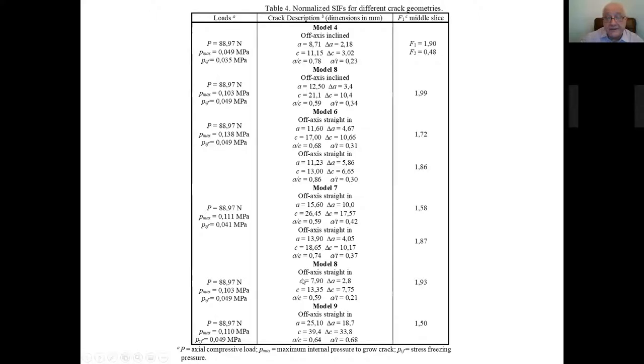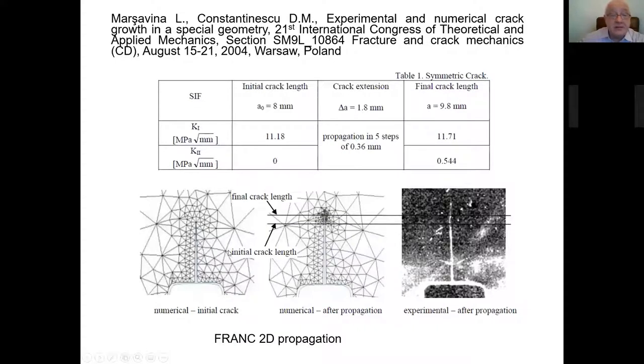So if you have a small propagation of the crack, in the middle slice, you have a higher value of this normalized stress intensity factor. If crack grows more, so this means close to 19 millimeters compared to 3 millimeters, this value decreases as the stress intensity factor is, let's say, readjusting itself towards all the surface of the crack. We tried also to make some comparison with numerical simulation done on Franc 2D propagation. And from the point of view of propagation by itself, of course, this is mode 1 propagation.